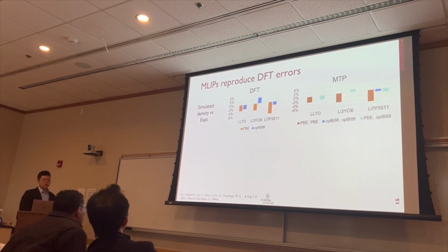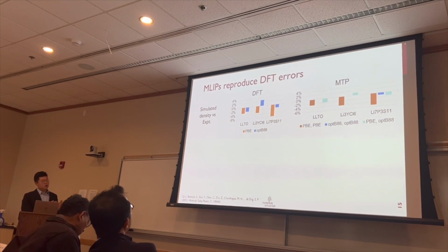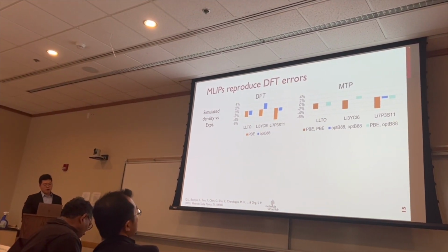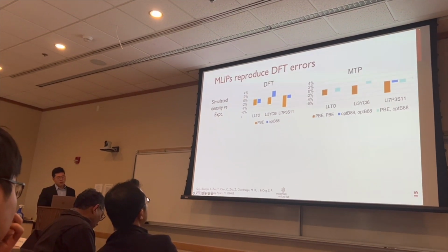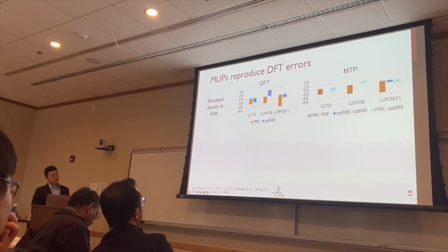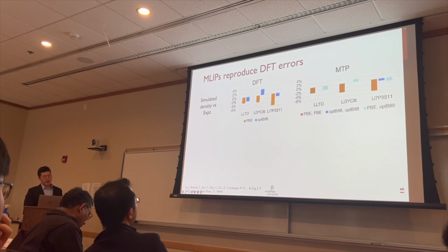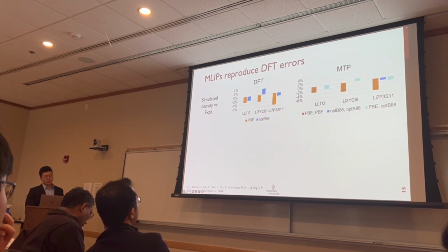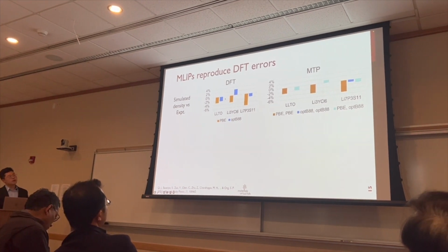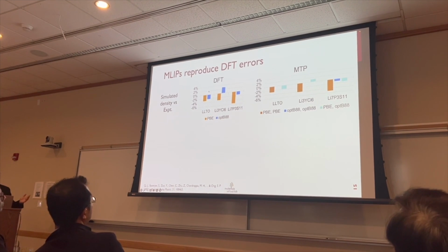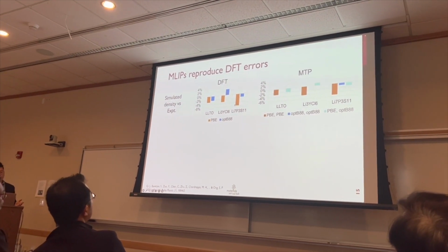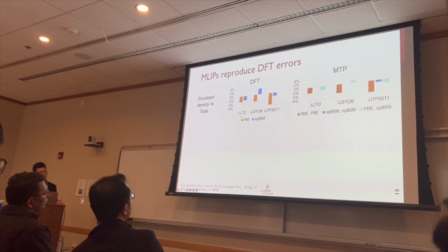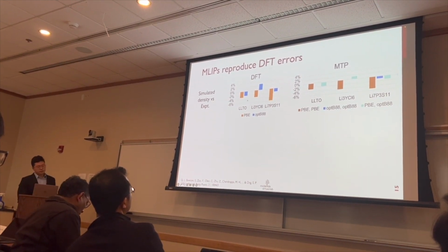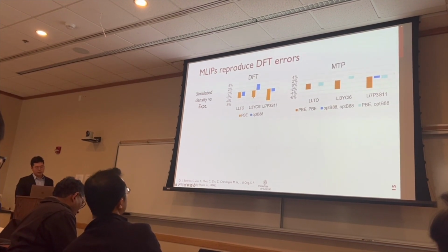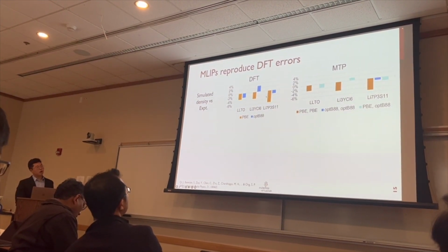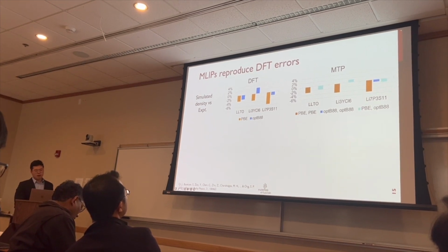And if we look at the simulation result of firstly the geometry relaxation with different methods, let's look at the DFT result first. This is the comparison of DFT result with experiment. The error bars show the result for different DFT functionals. For LTO, we can see that these 2 functionals give a similar result. While for LYC and LPS, we can see that PBE significantly underestimates the density by around 3 to 5%, while optB88 has overall better accuracy for the density of the structure.